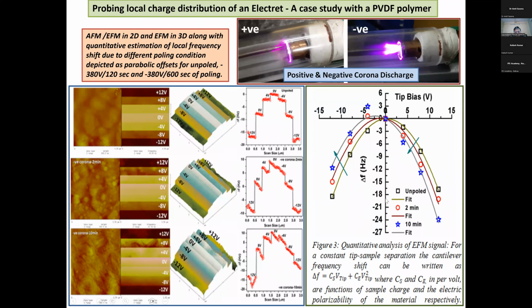system, okay, with a non-symmetrical parabola, and you can shift it. This is a second order equation, the resonance frequency shift. I told you the tip is vibrating, and that vibration frequency will change. When the frequency changes, the phase also will change, so amplitude also will change. So you can keep the amplitude constant and do frequency mapping like I did, or keep frequency constant and do amplitude mapping, or both, but keep only the phase changes for phase contrast microscope.